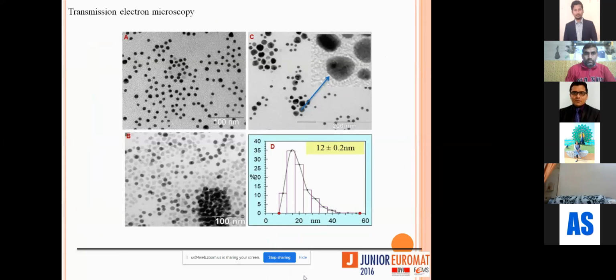And we have also conducted the electron microscopy, where we could see the iron oxide nanoparticle getting accumulated inside the sphere system, and you can get to know how the pegylation has taken place in the third diagram in the C section. You can easily see how the silane or carboxylic group, how the core-shell is working with that, how the functionalization is working with that, and how the iron oxide is getting incorporated inside that, or how you are able to achieve the polymer onto the surface, you can see with the help of this diagram.